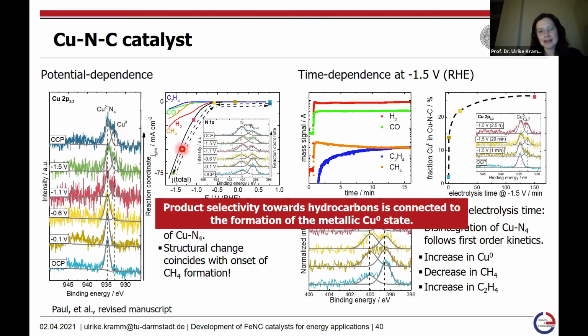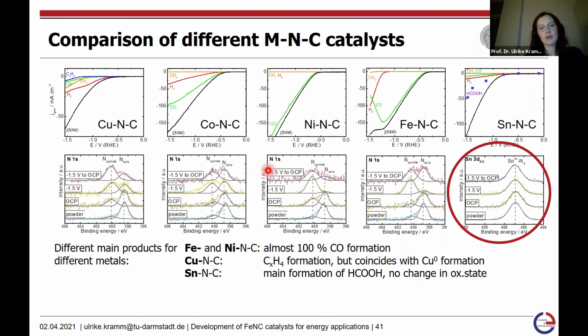And based on that, it's not really the metal N4 center that seems to be related to the hydrocarbon formation, but it is just the metallic state. Probably you might be able to get a finer distribution of the copper nanoparticles, but it's in any way not a molecular site which is related to the hydrocarbon formation for this type of catalyst material. We continued the study a little bit with comparison of other metal centers within the catalyst material.